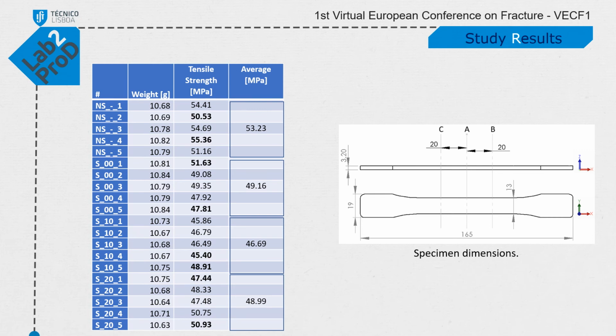On average, tensile strength of specimens with a seam is 7 to 12% lower than specimens without one. Seam dimensions show to have little influence on the tensile strength of specimens.